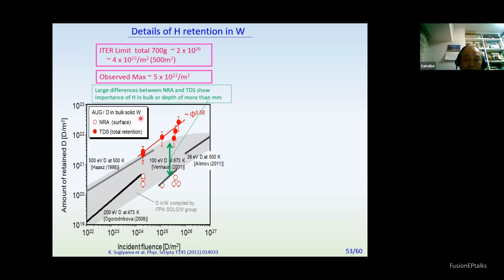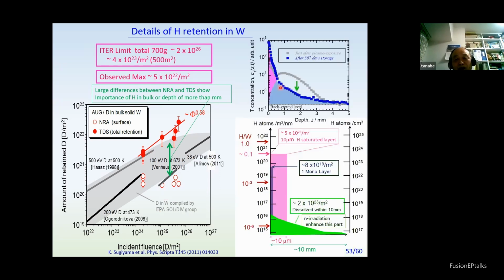There are also differences between bulk retention and surface retention, and this is quite consistent with this picture. The surface, near the surface, shows very high trapping. Depending on the thickness, nearly a similar amount, about 5 times 10^23, is trapped in the surface, while diffusion in this case gives a little bit larger penetration, coming to nearly the same level. But this part is easily released after removal of implantation, and only the surface-trapped part remains.